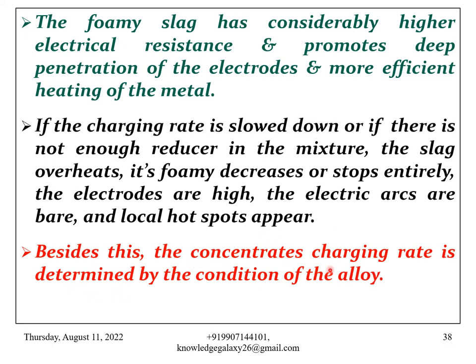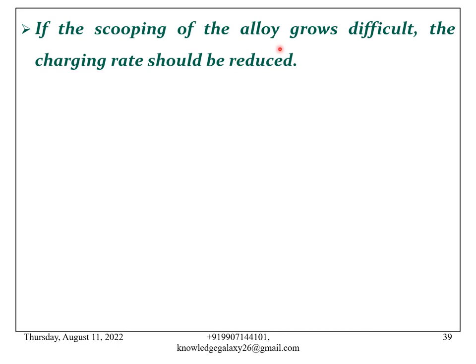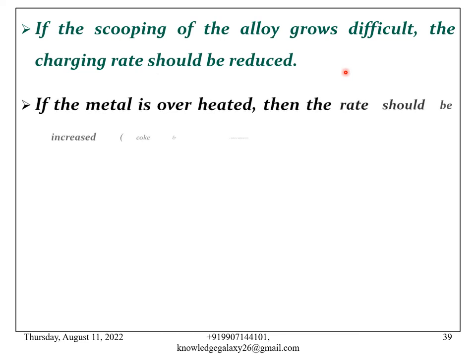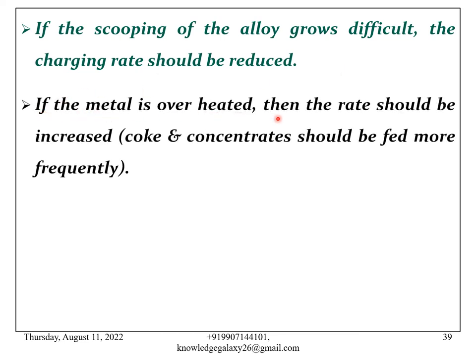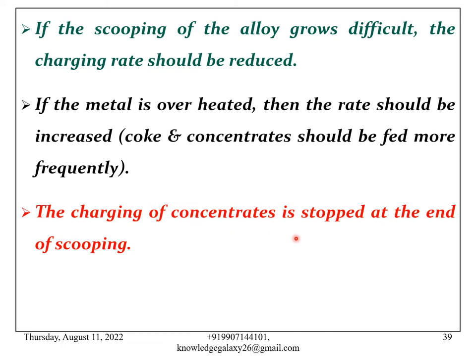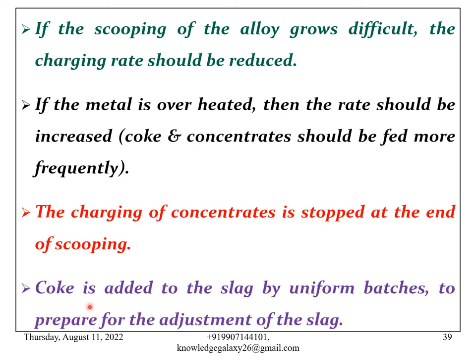Besides this, the concentrate's charging rate is determined by the condition of the alloy. If the scooping of the alloy grows difficult, the charging rate should be reduced. If the metal is overheated, then the rate should be increased, that is, coke and concentrates should be fed more frequently. The charging of concentrates is stopped at the end of scooping. Coke is added to the slag in uniform batches to prepare for the adjustment of the slag.